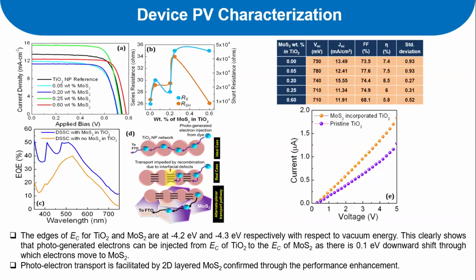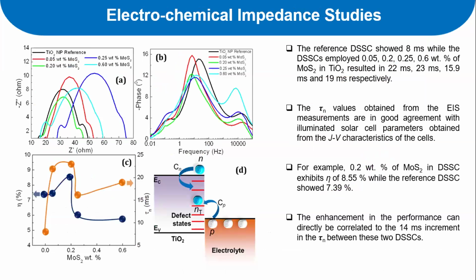But when we increase it, it impedes. The reason is it agglomerates, and the excess 2D layer semiconductor doesn't help in the photo absorption as well as charge transfer. So there is an optimum value. Further, we just wanted to justify why this enhancement is happening. If we include the 2D layer semiconductor in the electron acceptor, then we observe through electrochemical impedance spectroscopy that the charge carrier lifetime is significantly increased.